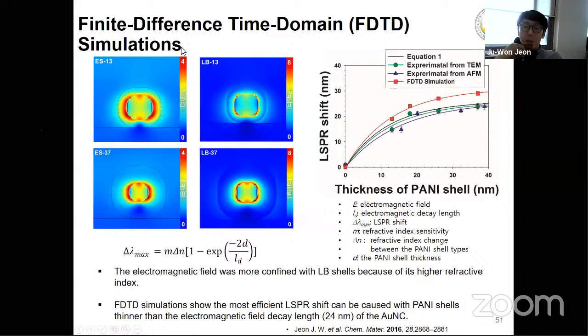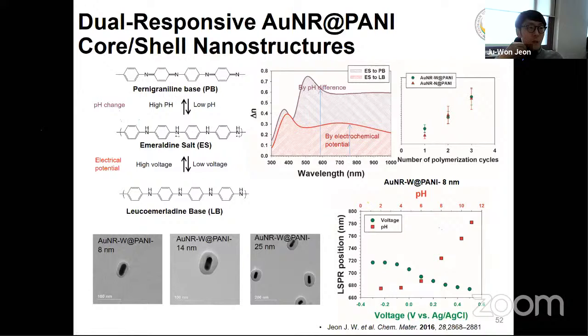So FDTD simulation was also performed, and the experimental result follows the theoretical LSPR shift. And after that, we also demonstrated the dual responsive gold nanorod and polyaniline core/shell nanostructures. So in this case, we use two different stimuli. The first one is the electrical potential, and the second one is the pH change. So we convert this LB to ES and ES to PB, and then the refractive index change is very high when the ES form is changed to the PB form.